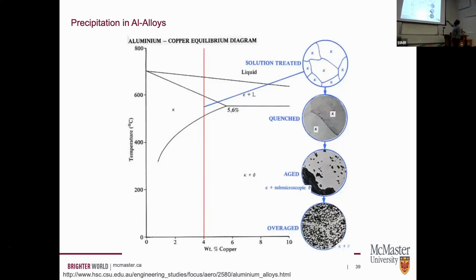And so you have this kind of single phase material, but it's polycrystalline. You quench it into this two-phase region, and then what tends to happen is it forms these precipitates that are supposed to strengthen the material. The idea here is the more obstacles you have in this material to defect motion, the stronger the material is.